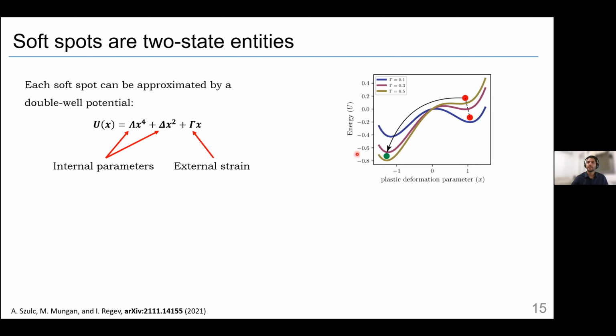So if we change the strain, for this example, we increase the strain, you can see that this minimum transforms to a saddle. And when it happens, the system switches to a different state. And it can happen in the other direction also, if we decrease the strain to the point that it pushes it to the previous minimum.